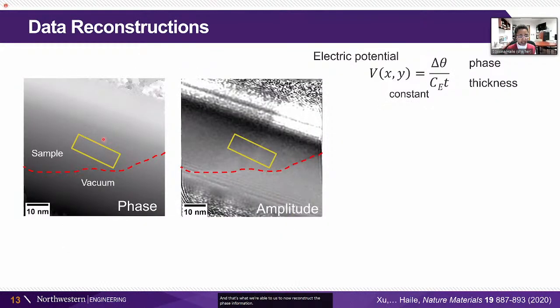And so here's the phase information again. You might think that the grain boundary is not there. It's even hard to see the sample edge, but they really are there. Here's the amplitude reconstruction. And the reason we need the amplitude reconstruction is that we are recognizing that the electric potential is given by this phase value divided by the thickness of the sample, and that thickness information is carried by the amplitude. So we use both of them to now reconstruct the electric potential profile.